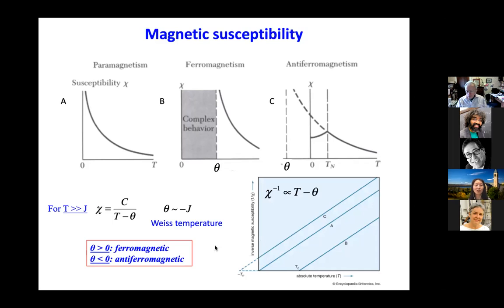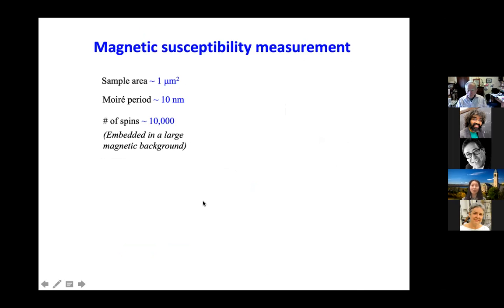And you can also just look at the 1 over chi and do a linear fit, and that's what experimentalists like to see. But we have some problem here. As I told you, we have a few atom thick sample with an area size of about a micron squared. And if you count the number of spins in that system, we have a total of about 10,000 spins. And those spins are not isolated. They are embedded in a large background, so any other material can also give you a signal.